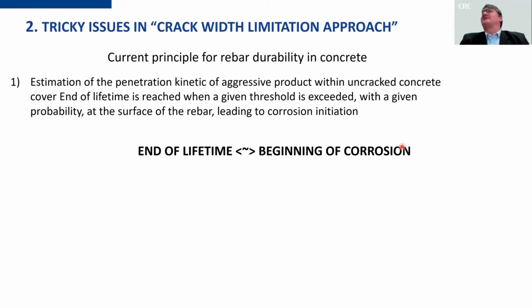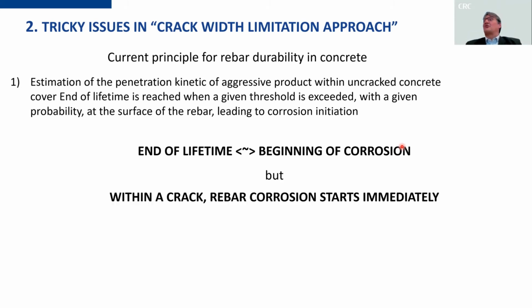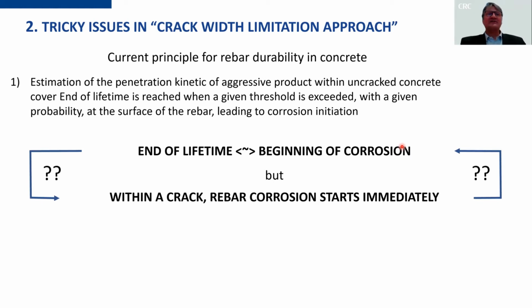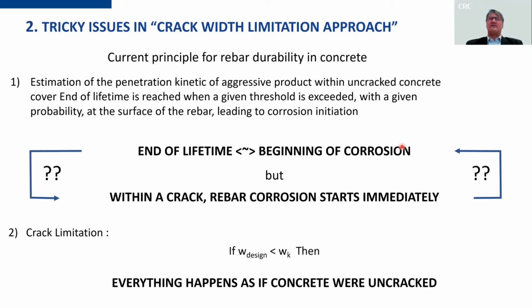But reinforced concrete, by essence, is cracked. And in a crack, the corrosion starts immediately. Not immediately in terms of seconds, or hours, or days, or weeks, but immediately regarding the lifespan of the structure. So there is an apparent contradiction. And this contradiction is solved by saying, if your design crack is lower than a given value, everything happens as if the concrete were uncracked. But is it true?